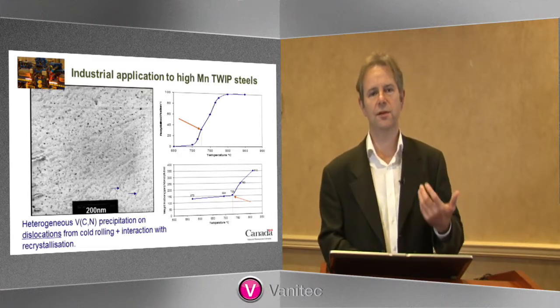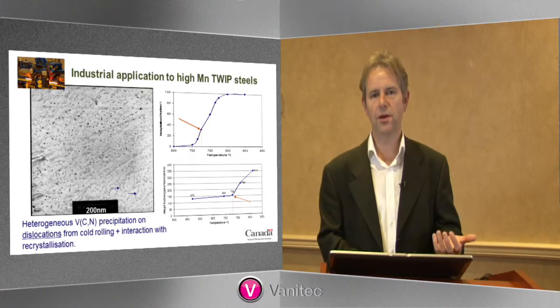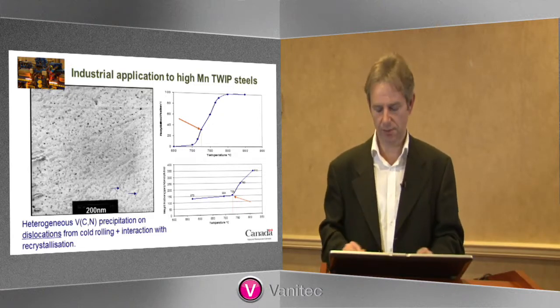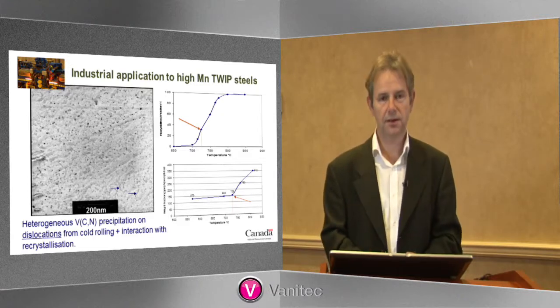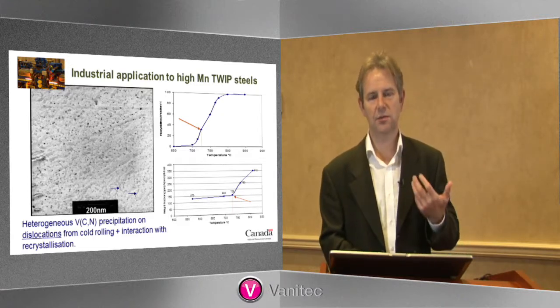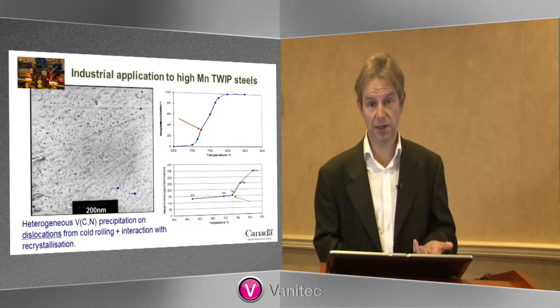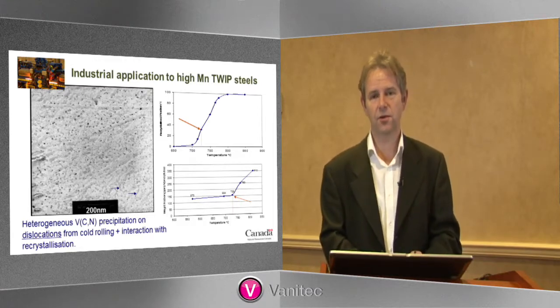Again, it's further proof that these things are forming on the way up and are not really forming during the isothermal annealing step. So that would be very interesting, because we would expect a much higher precipitation density when they're formed heterogeneously on dislocations in this case.